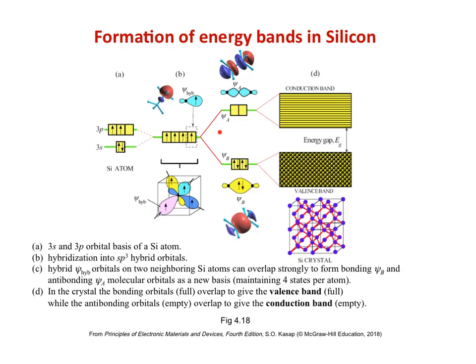With 4 molecular orbitals participating per atom in bonding, we result in 2 bonding orbitals per atom and 2 antibonding orbitals per atom. In the case of silicon, with 4 electrons per atom, we have an entirely filled bonding molecular orbitals and entirely empty antibonding molecular orbitals, giving us the strongest bonds possible.